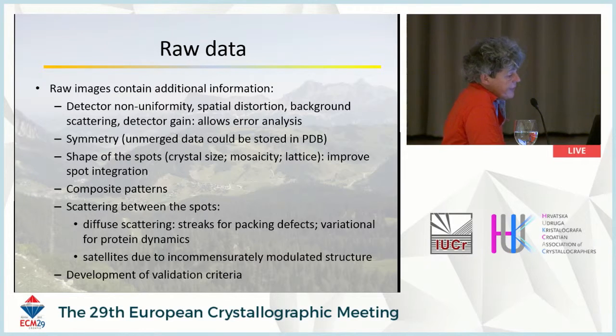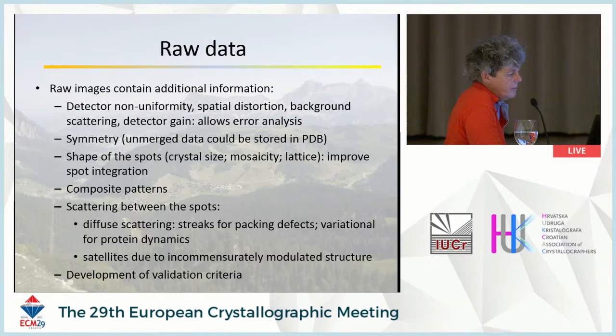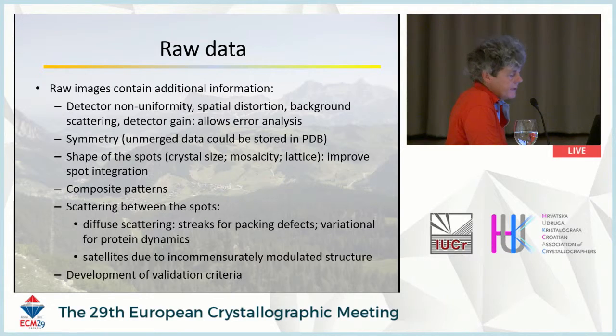The shape of the spots depends on many things: crystal size, beam divergence, mosaicity, and the particular lattice. In the future, reanalysis could allow better spot integration. There are also composite patterns, twins, and triple lattices that may have been overlooked or ignored by the researcher but are still present in the data.